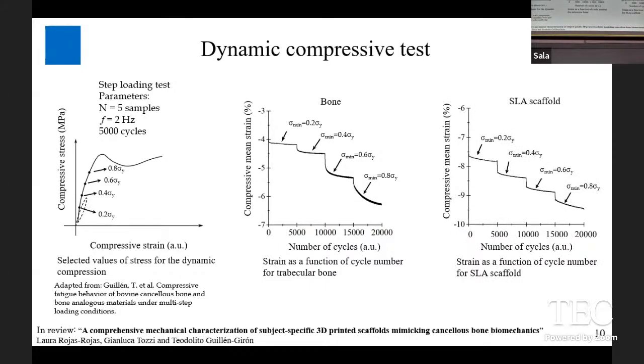This is the mean strain as a function of the cycle number. The main thing that I want to point out here is that the mean strain per each cycle remains quite similar, which shows us that the scaffold doesn't have a lot of deformation accumulation, let's say. When the strain increases sharply here is when the load also increased during the test.